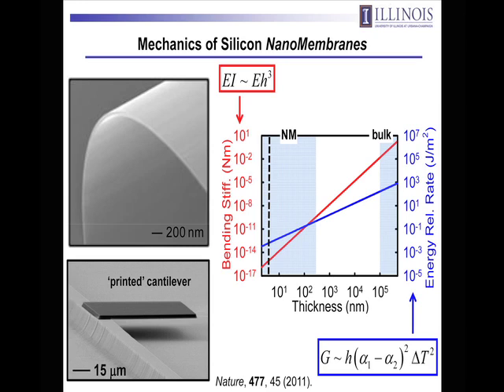And so as a result, as you go to this silicon nanomembrane regime, the interface energy release rates decrease substantially, such that it's much easier to get sheets of silicon to stick to a substrate than it is chips of silicon. As a result of that linear decrease in the energy release rate, these nanomembranes are functionally sticky to almost any surface you want to integrate the silicon onto. So you can easily get it to bond to plastic or rubber, whereas getting a silicon chip to do that is very difficult because of that linear scaling of the energy release rate with thickness. So that's why we like nanomembranes as building blocks, as sort of favorable mechanics associated with this thin geometry.